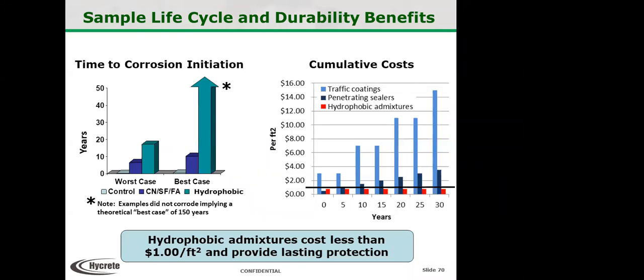And you can see that the hydrophobic did best in the worst conditions and their best conditions. Now there's an asterisk there. You guys might ask, why is there an asterisk? Well, it's a theoretical best case scenario for 150 years, which by the way, even that is an estimate, because up until then, the average life cycle of any structure, with all of the theoretical modeling, was about 75 years. 150 was the max case scenario because no one ever got close. It was that bar that no one could ever break until we came to be tested. At that point, there was no signs of corrosion in their simulated model of 150 years. We literally broke the test. So there's an asterisk there because the answer is it probably could have been more than that, but they'll never know.